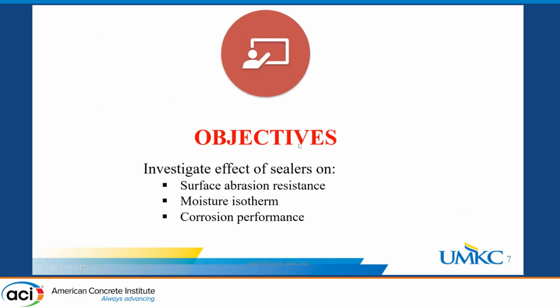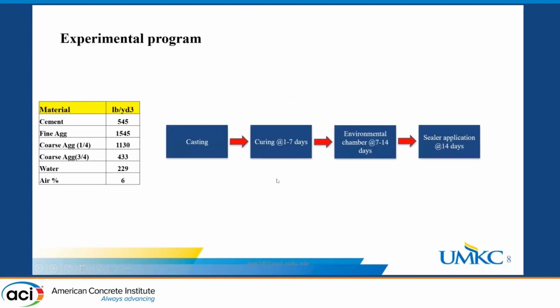So I come to the objective of my research. I want to use penetrating sealer as a very economic material that is very easy to apply on reinforced concrete structures. I want to see the effect of this material on durability concerns such as surface concrete abrasion, moisture isotherm, and corrosion performance. To do so, we designed our concrete mixtures, cast our concrete, cured it for 7 days, transferred it to the environmental chamber for 7 days as well, and applied the sealer at the age of 14 days.